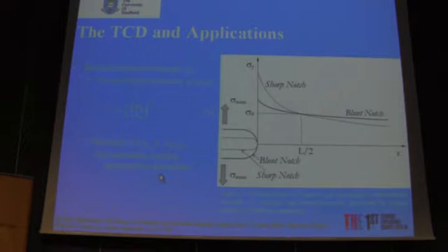On the contrary, if the failure is accompanied by a certain amount of plasticity, sigma naught seems to be larger than sigma UTS. In this case, the only way to determine sigma naught and the critical distance L is by running appropriate experiments. To run experiments, we can use figure 2 as a strategy to define sigma naught and the critical distance L.